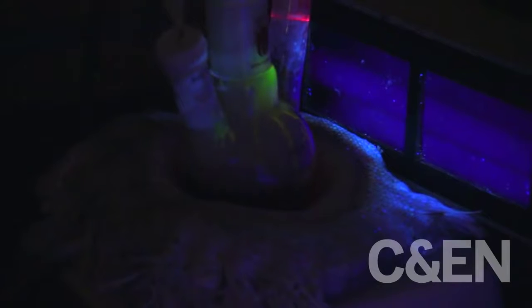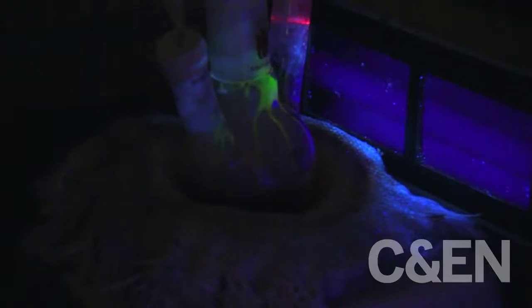So now I am injecting the selenium, and you can see the color changes immediately. I'm going to lower the temperature to 290 degrees to anneal it. You can see in the beginning it fluoresces green, but as it heats up it turns to a more red color. So now we just wait about 12 minutes while this anneals.